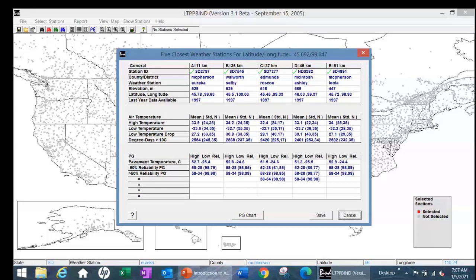It gives us, for that particular area, in this case Eureka, South Dakota, what is okay for its temperature and climatic conditions. The algorithm will rate me out at 52.7 to minus 25.4, which means for 50% reliability, I should be using a 58 minus 28 oil. And if I want to bump it up, essentially it's the low temperature side, which makes sense, right? Eureka is 58 minus 34.